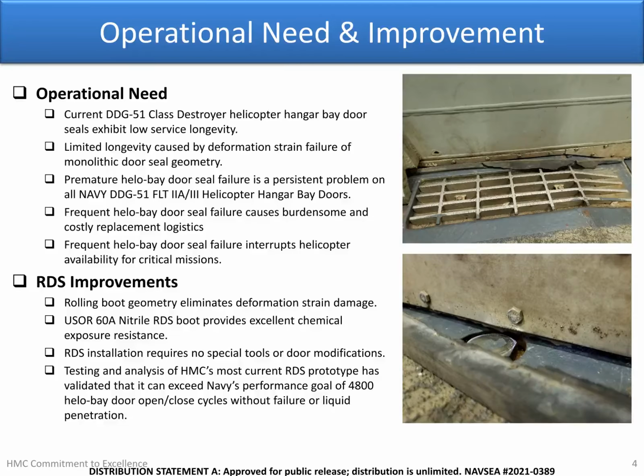The DDG destroyer helicopter bay door seal, currently deployed by the U.S. Navy, exhibits unsatisfactory in-service longevity because of material failure caused by large bending stresses that exceed the yield strength of the monolithic-shaped seal. As the helicopter bay door is closed, the rectangular monolith seal is forced to bend through an angle that approaches 90 degrees.